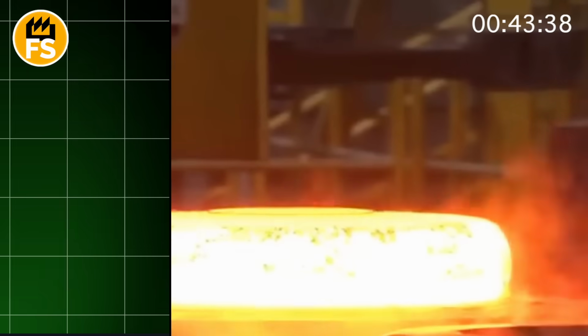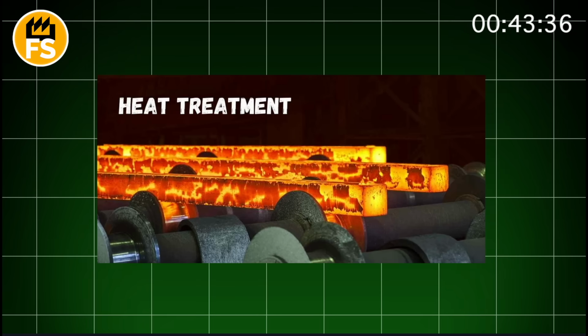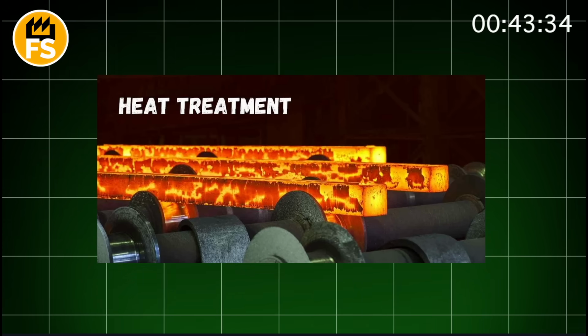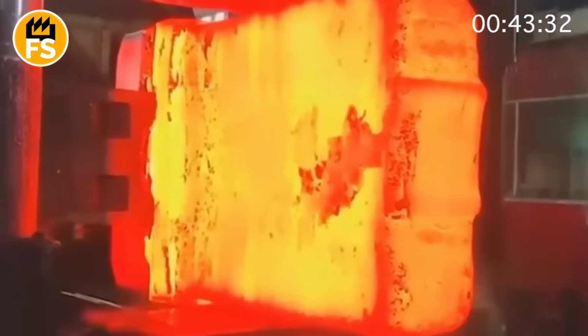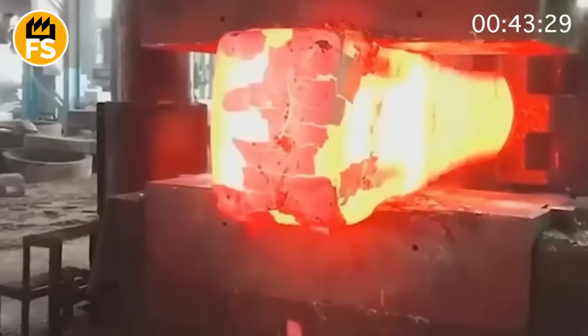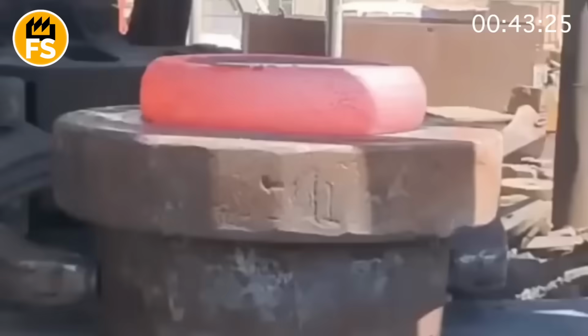After rolling comes the most important stage, which endows the wheel with its unique dual properties: heat treatment. The wheel must be both hard and tough at the same time. Its running surface must be extremely hard to resist wear, while the plate and hub must be softer and more ductile to absorb shocks and not crack.